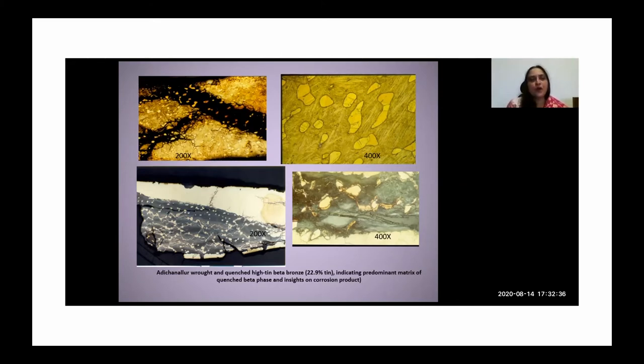The one on the top, at low magnification, shows the two-phase structure that I was talking about: the small islands of alpha phase, which have the annealing twins that come from the hammering. And in the background you see this matrix, which looks uniform at lower resolution. But in high resolution, you see the needle-like beta phase. You have to look at a higher magnification, and it has to be etched appropriately to bring out that needle-like phase.